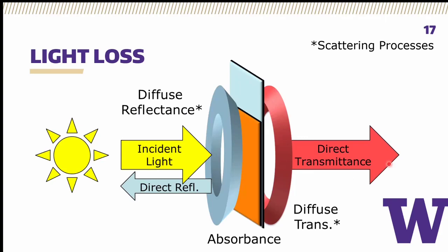In other words, what is throttling the direct transmission of light below the band gap of our methylammonium lead bromide? Again, above the band gap, you would have this light being absorbed by the perovskite material and converted to electricity. But you'd want all the light that's below the energy of the band gap of methylammonium lead bromide to directly go in this direct transmission bin and be incident on the invisible cadmium telluride device that you see on the right side of the screen here. In reality, you have a lot of mechanisms that can contribute to loss of throttling of this direct transmission, including direct reflectance, specular reflectance of incident light, and these scattering processes, diffuse reflectance and diffuse transmittance, which come about due to surface roughness and interfaces when light sees a lot of different indices of refraction in very close proximity, and therefore light is then reflected in a random orientation in 3 space off of your sample.